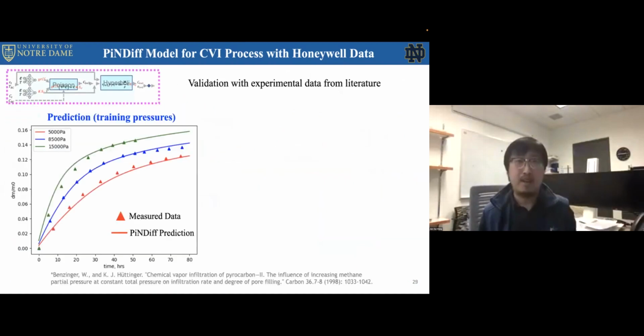So this is what we did, and we actually used experiment data from the literature. The literature data has weight information during this manufacturing process, and they basically measure the weight of the samples. Once they cook the sample for a while, they take it out and measure the weight, and you get those sparse weight points or mass measurements. And they do it for different partial pressures of the reactive gas. So these three different colors represent three different partial pressures. Okay, so we're going to use this data. It's pretty sparse, for three different partial pressures, and train our models.